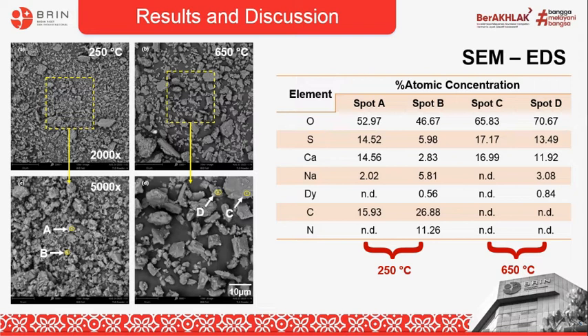The spectroscopy analysis showed the expected elements of the base material, that is calcium, sulfur, and oxygen, while the detection of sodium indicated the presence of another phase that was undesired. The XRD measurement was conducted to confirm it.